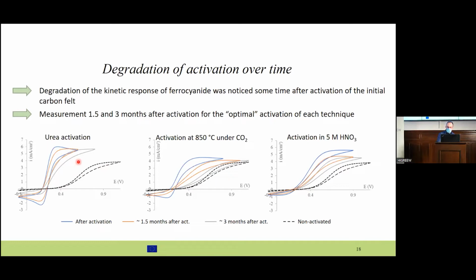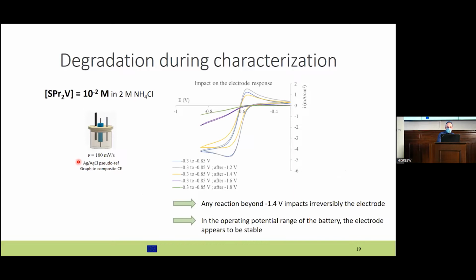So we have to be aware that after activation, the material is slowly deactivating, and we have to pay attention to that, so that the activation protocol we are choosing is the most stable with time before implementation in the battery. And one more notice is that this measurement can also be used for following the stability of the